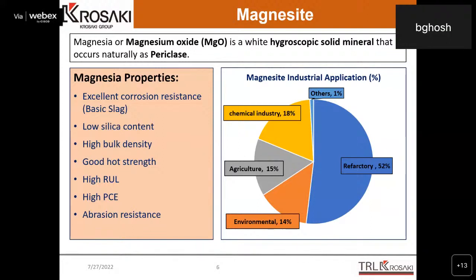And in the environmental sector: soil and groundwater treatment, waste treatment, drinking water treatment, and magnesia has the capacity to stabilize dissolved heavy metals. So these are the applications. But what is the beauty of magnesia for refractories? It has excellent corrosion resistance when coming into contact with highly corrosive basic slag, particularly high calcium oxide around 45 to 50%, SiO2 around 25 to 30%, and alumina-containing slag. This highly corrosive slag is encountered in the basic oxygen furnace, steel melting, and ladle refining processes, where MgO grain offers excellent corrosion resistance towards this slag, particularly with low silica content, high bulk density, good hot modulus of rupture, refractoriness under load, high pyrometric cone equivalent, that is fusion point, and abrasion ratio. So this is the beauty of magnesia, which offers excellent behavior in refractory aggregate.